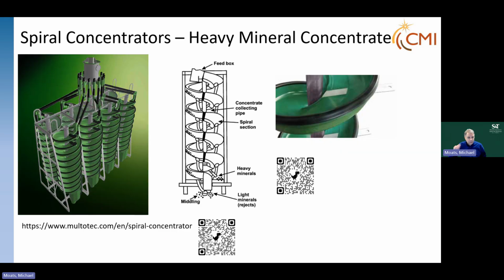So let's talk about those in a little more detail. Spirals are a very easy technology. Essentially, it simulates a river bend. As the slurry goes around the spiral, the lights tend to come to the outside and the heavies come to the inside. You can then open up ports towards the inside by moving these levers. The heavy minerals get collected on the inside and the lights come on the outside, and we end up with different feeds, a light material and a heavy material. A lot of times the lights are rejected and sent back into the pit where the sand was dug up, and the heavies move on to other processing.